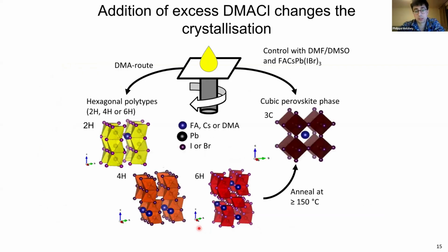And so what happens with this change is that the moment we add this DMA route, after the first immediate annealing, the films are actually not black, but rather yellow, orange, or red. And these indicate hexagonal polytypes. So for FAPI, one would call this the delta phase, but for us, it's the intermediate structure which we form before it goes to the final perovskite. And you can clearly see it visibly. And then only upon the second annealing step, if you go to 150 degrees or higher, the films start changing and go into the cubic perovskite phase. And normally if you use the DMF-DMSO one with the FA-cesium, you almost immediately go into the cubic perovskite phase.